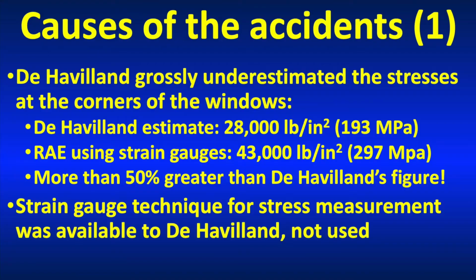So now, as we move to a close today, if we look at the causes of this accident, the first one, and I think really de Havilland needs to be hammered for this, they grossly underestimated the stresses at the corners of the cutouts like the windows. And in fact, when the RAE did their investigation and looked at this using the strain gauge technique, they found the actual stresses there were half as much again as de Havilland thought. Now, the strain gauge technique was developed in 1938, so it had been around for 10 years by the time de Havilland came to design the Comet. If they'd used that technique, they would have known immediately how high the stresses were at the corners of the cutouts, and they could have done something about it.